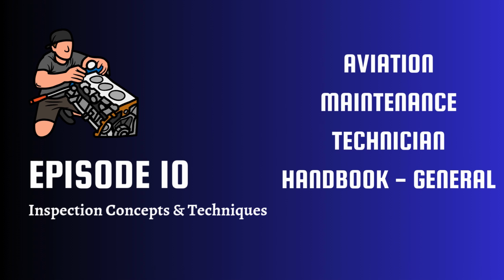So what's the simplest check for composites? The most basic first-level field evaluation for accessible, relatively thin composite skins, the sources say generally less than about 0.080 inches thick, is tap testing, sometimes called the coin tap test. You literally tap it with a coin, or a small, lightweight tap hammer made of plastic or aluminum. You lightly tap the surface across the area of interest and listen carefully to the acoustic response, the ring.